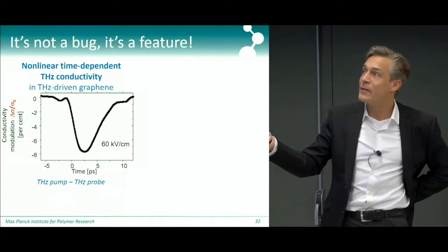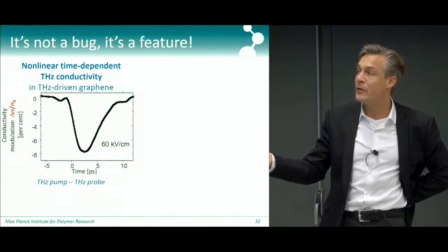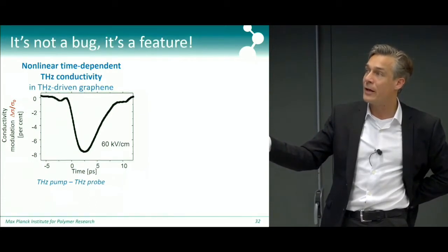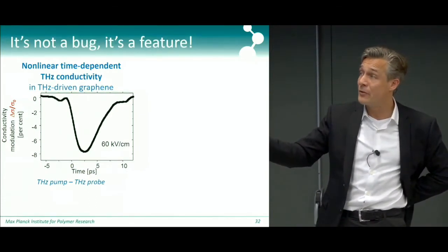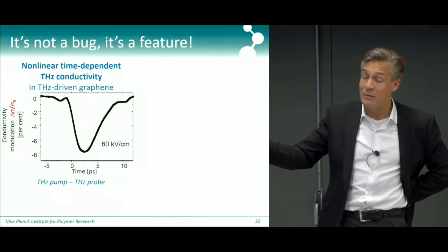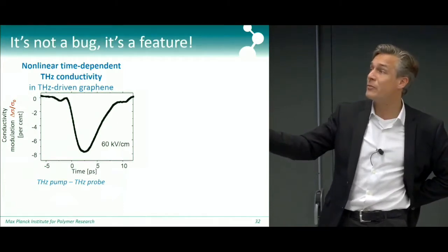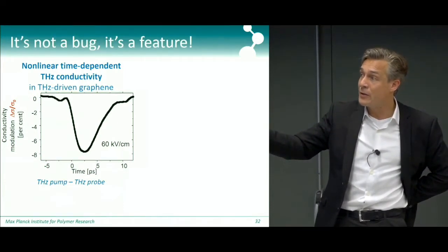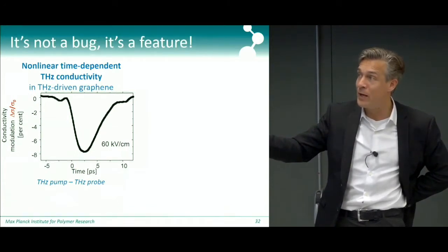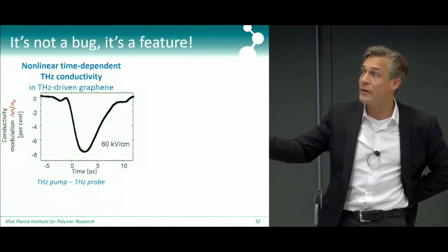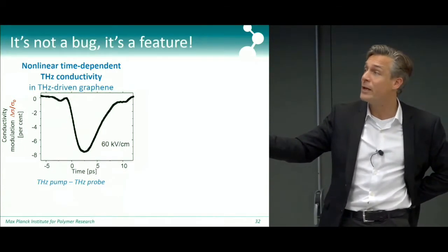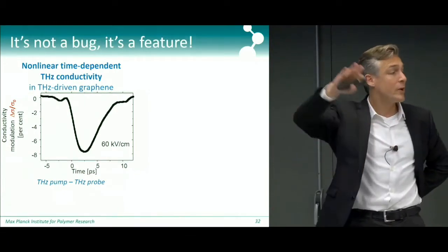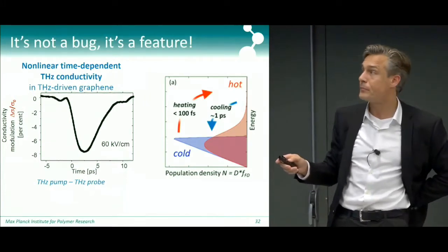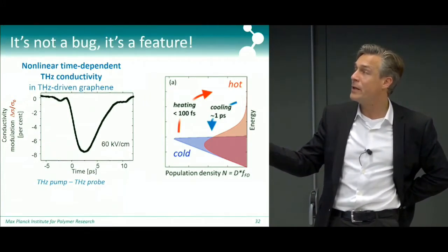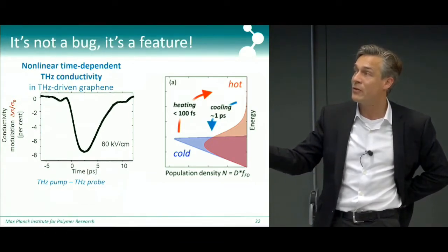And so that we can get this nonlinear time-dependent conductivity is apparent from this measurement here, where we did a terahertz pump, terahertz probe measurement. So now, just like with the optical excitation, we get basically a reduction in the terahertz photoconductivity, if you will. And so this is basically the terahertz excitation pulse that is heating up all the carriers, that is reducing the conductivity, and this modulation is several percent, and then the carriers cool and the system regains its original conductivity. And so this heating occurs very quickly, and the cooling occurs on this time scale here of about a picosecond.